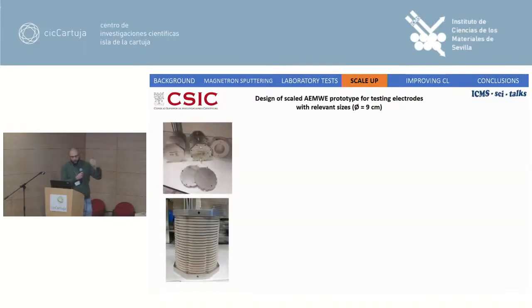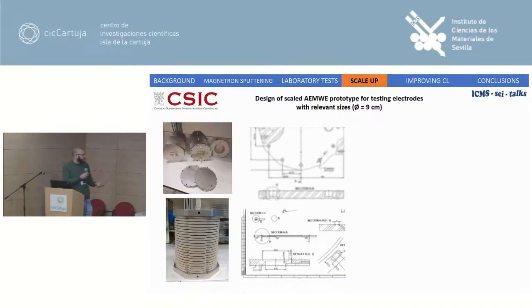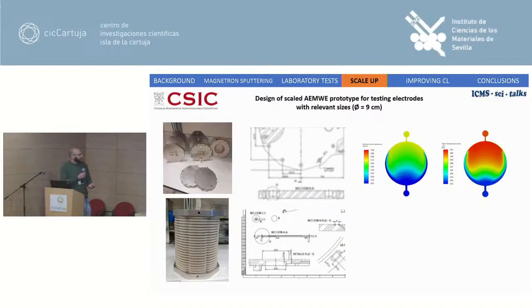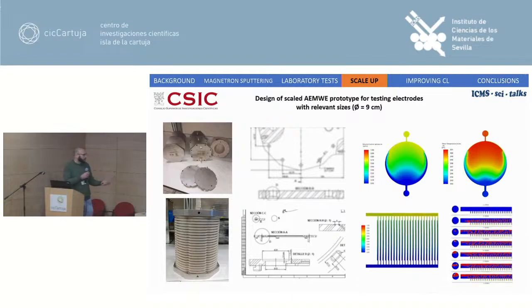So at this moment we have the electrode, but we need a device to test it and prove its electrochemical performance. So we manufactured a prototype of an anion exchange membrane water electrolyzer with 20 cells. To manufacture it, it was necessary to design the manufacturing plans, and we also had to simulate some experimental conditions such as the gas and temperature distribution, and, of course, to simulate the working behavior of this prototype in a 20-cell stack. We can also see here how we were able to simulate even the oxygen evolution at the exit of the